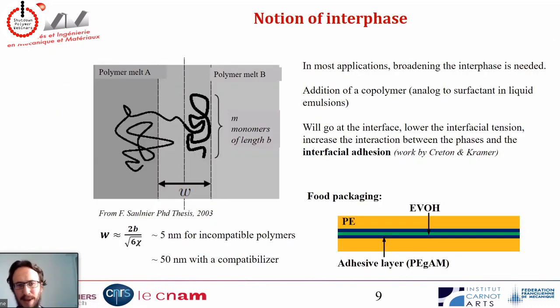So the molecular reason for that is the interface between the two polymers. The interface is the region between the two polymers in which the polymer blend mixes, and this region is really small in thickness. For immiscible polymers, if you put some numbers in this, where b is the length of the monomer and chi is again the Flory interaction parameter, for incompatible polymers this number is only a few nanometers. So only a few monomeric units are actually binding the interface. That's why it will detach really easily. It's below the entanglements in this region, so it will detach really easily, and the films won't have any mechanical